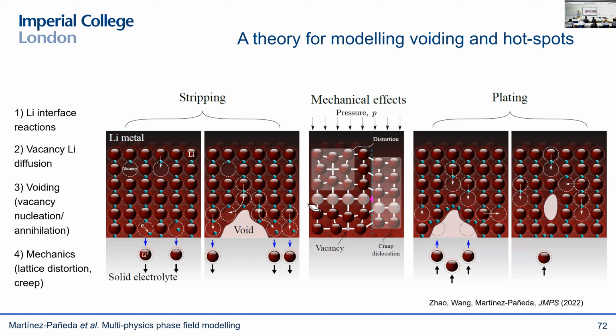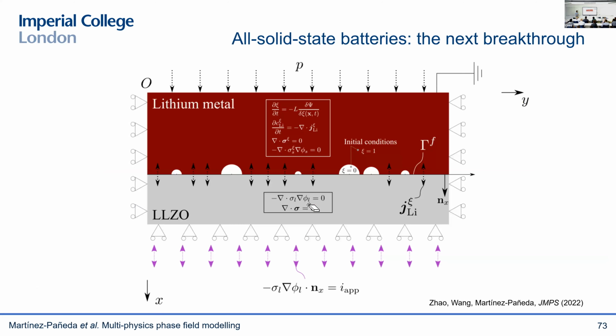You need to capture the voiding process, how those voids evolve, how they interact with each other. This is very suitable for phase field, of course, so you need to define a suitable phase field evolution equation. And then you have a lot of mechanics as well, because, first of all, you have lattice distortion due to these chemical strains, but also, most importantly, the main hypothesis in the battery community is that they will be able to solve all these problems by applying a stack pressure. So they apply a constant pressure, and therefore the creep and the deformation of the material will basically shrink those voids and eliminate the voiding problem. What they don't know is exactly how much pressure they will need to put in there, and so on and so forth. So this is where the model comes into play.